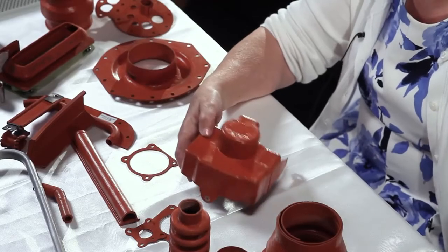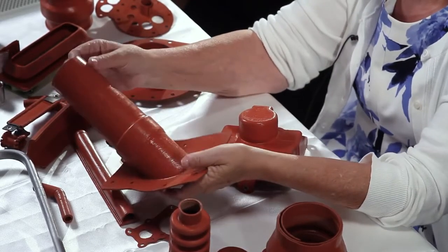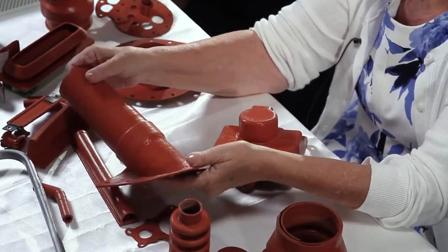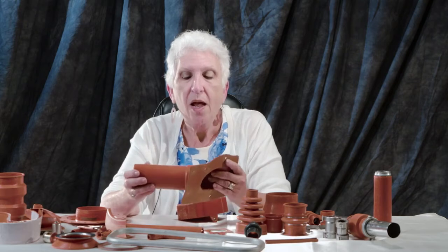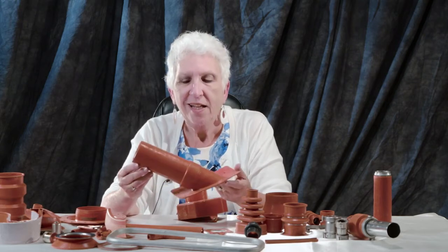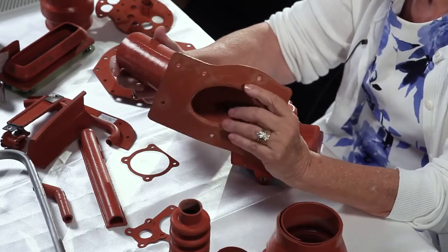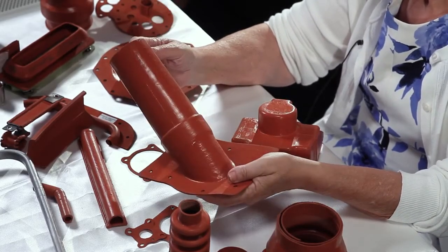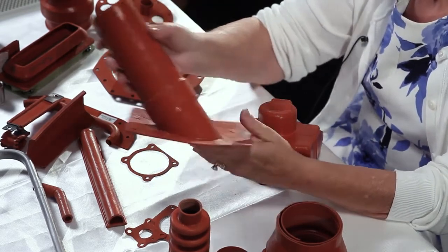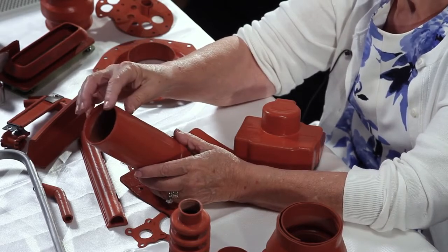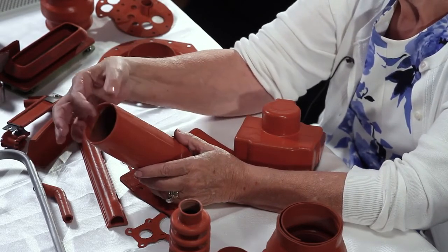The final new property is insulation. We started with this part in 1993, where we got a very interesting phone call from engineers who were actually developing the Lear 45. And this is why I love engineers. They had an 800-degree tube going directly through an avionics cabinet where everything melts at 200 degrees. So they asked us if we could insulate that duct. We'd never done it before, but we developed this using a new material. It's 90 thousandths thick, and bonded within this 90 thousandths is a sheet of a material called Fiberfrax.